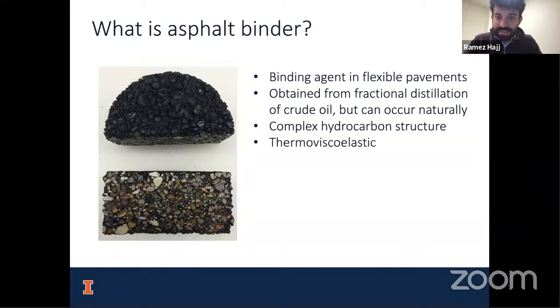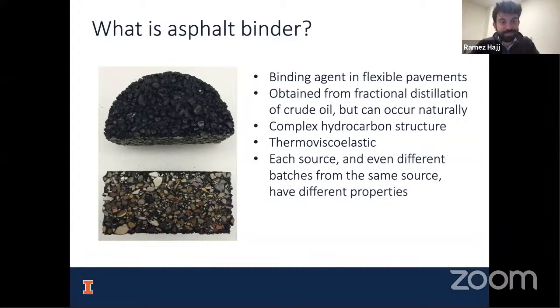The other thing that makes asphalt binder extremely interesting to researchers is its thermoviscoelasticity. So this material behavior is not the same at all temperatures, and it also even depends on the loading rate. So if you load this material quickly, you will see it has a stiffer behavior, and if you load it slowly or have slow traffic, you will see it has a softer behavior. And this primarily dictates all of the things that I'll explore in this presentation.